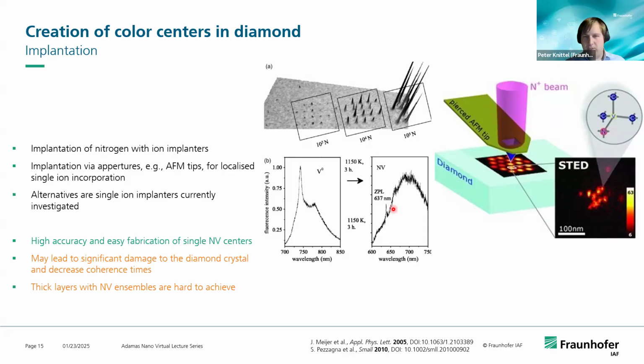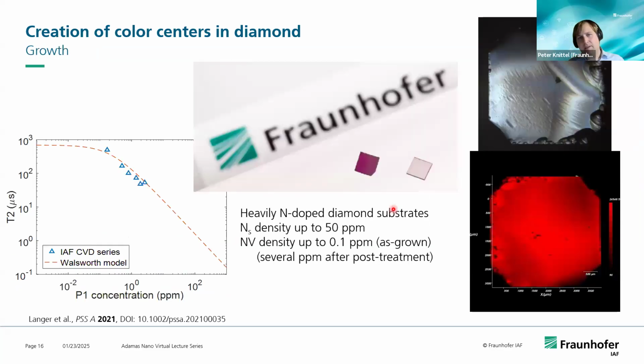This is where the CVD growth comes into play. And you can easily incorporate nitrogen in diamond. So the incorporation efficiency is rather high, in the range of 10 to minus 4. And with that, you can produce NV densities in the ppm regime if you do a post-treatment. So here again, you see these nice red colored diamonds. These are some diamonds that contain NVs in the concentration of 1 ppm and above, but also lower levels can be achieved.